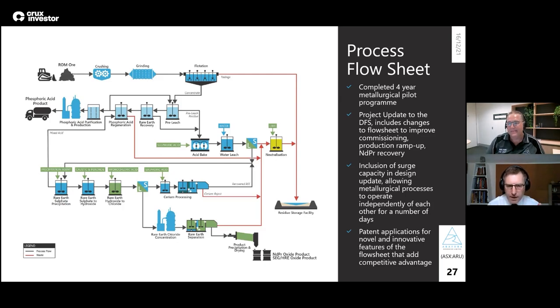Forgive my poor understanding of metallurgy or hydrometallurgy. When you talk about an acid bake, you're heating. It's more like an acid boil, really. It's a saucepan equivalent. You're heating the fluid up, not heating a dry cake. So for every ton of residue we have, we mix 1.6 tons of concentrated sulfuric acid with it, and that forms a paste, and then we heat that up, in our case, to 250 degrees. In Lynas's case, they have an acid bake, but they mix this paste and then heat that paste up to 700 degrees and produce a dry discharge from their kiln. So they have great big long, 200-300 meter long kilns. We do all this in a paddle dryer. Okay. Thank you.